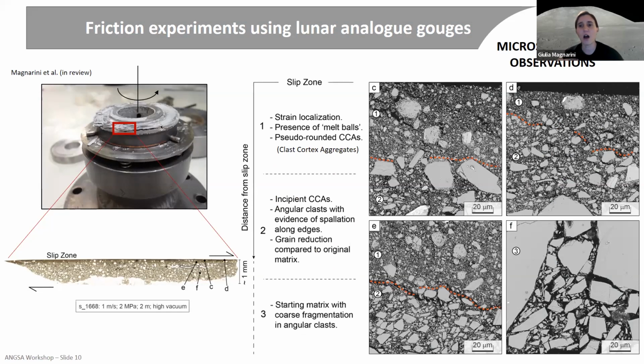So we also made some microstructural observations. So we took fragments of the sample after running the experiment, made thin sections, and then we observed with the scanning electron microscope. And so here on the right-hand side panel, the slip zone is at the top of the figure. And so moving down, we move away from the slip zone. And we identify 3 distinctive microstructural zones, each containing or not some type of clast fabric.